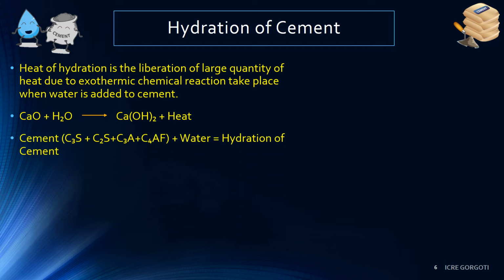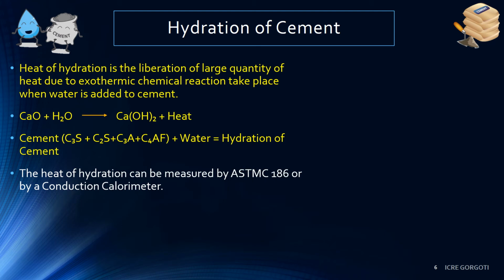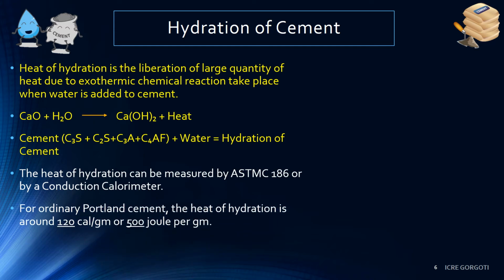But in case of cement, lime is combined with all constituents of cement and compounds are formed. So these compounds are responsible for hydration of cement when cement comes in contact with water. The heat of hydration can be measured by ASTM C186 or by conduction calorimeter. For ordinary Portland cement, the heat of hydration is around 120 calories per gram or 500 joules per gram.